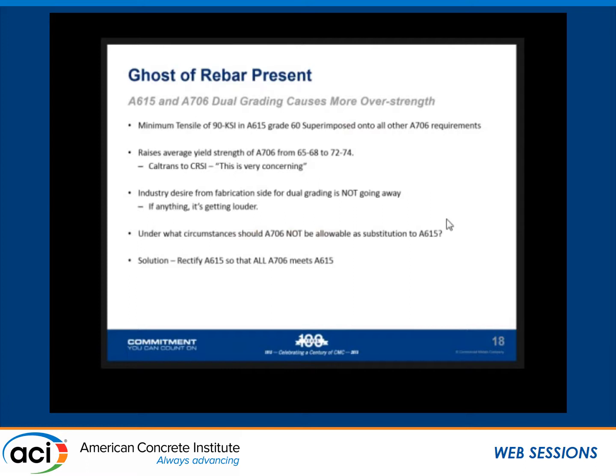Now taking a look at something else, your minimum 90 KSI tensile on A615 is actually impacting A706 because of the market demand for dual grade. What's happening with the dual grade is everybody wants the bar to hit both grades. We bring the strength up to make sure we hit the 90 minimum. The yield strength comes up with it. Now we're averaging 72 to 74 instead of 65 to 68. Nobody wants the overstrength, but the grades are misaligned, and that misalignment is directly causing this phenomenon.